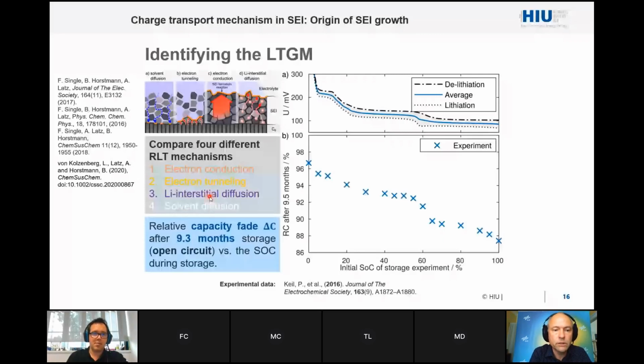DFT simulation, which said that there is one mechanism which has to be considered, namely an interstitial-mediated transport of quasi-neutral lithium from the electrode across the SEI to the electrolyte where the electrolyte is reduced. I cannot really go into the details here. First, I want to say the most favorite one which we found is the lithium interstitial diffusion.